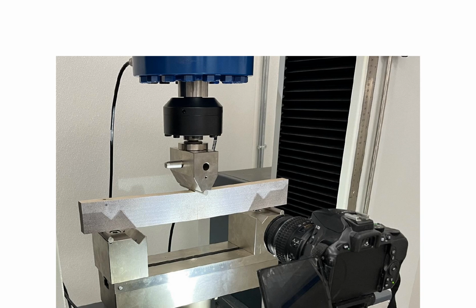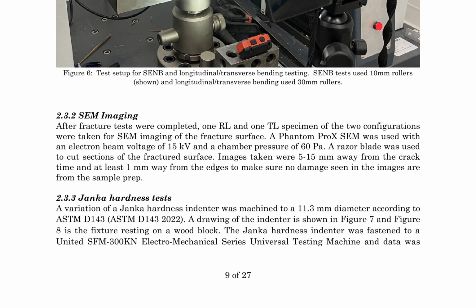These tests aim to assess the material's resistance to crack propagation and bending strength under different loading conditions. Following the fracture tests, scanning electron microscopy, SEM, imaging was conducted on selected specimens to examine the fracture surfaces. A Phantom Pro X SEM with an electron beam voltage of 15 kV and chamber pressure of 60 pascals was employed. Images were captured 5-15 mm away from the crack tip and at least 1 mm away from the edges to avoid any damage caused during sample preparation.